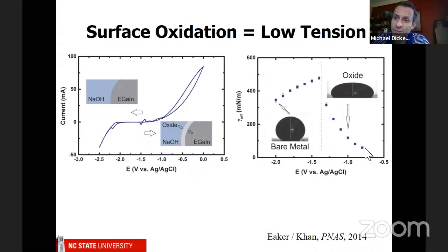I think it could have to do with charge on the surface, depending on what the chemical species are that are forming. And it could also be due to driving charge through the oxide layer. So if you imagine you have an oxide layer and you drive charge through it, that pushes the oxide outwards and generates a stress.